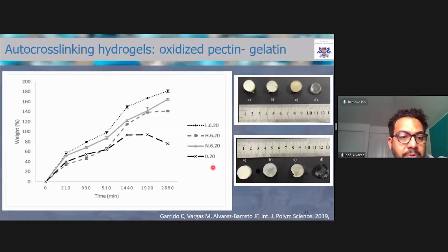And we found very interesting differences in swelling behavior. This curve that you see here is hydrogels with native pectin, pectin that hasn't been oxidized. And you see that the swelling starts decreasing, which means the hydrogels start to degrade. And we actually saw that in the lab. The swelling was also controlled by how much of the oxidized pectin you put in.